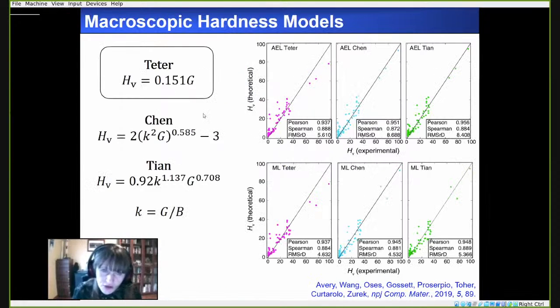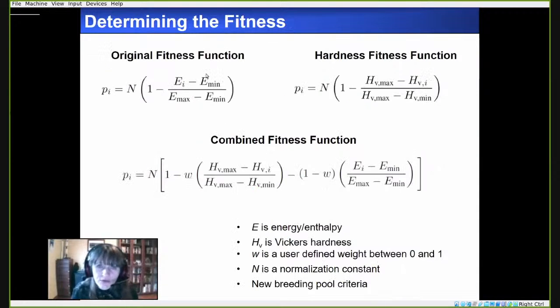So first we wanted to determine which macroscopic hardness model is the best to use. All of the ones that we looked at had a relatively good agreement between first principles, machine learning, and also with experiment. However, the Teter model was the most robust when looking at hypothetical structures that were created, for example, during the structure search. So the fitness function that we employed in the new algorithm combined both the energy of the structures and also the Vickers hardness that was estimated by using the Teter model.